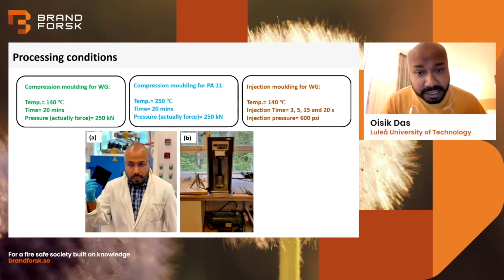So there are different processing conditions for this, where for the compression molding, we have 140 degrees, pressing time was 20 minutes, and the pressure was, well, actually its force was 250 kilonewton. For polyamide 11, we have used 250 degrees centigrade. This depends on the melting point of the plastic. We have to choose a processing temperature which is equal to or higher than the melting point of the plastic we are processing. So for polyamide 11 or nylon 11, we chose 250 degrees centigrade. The pressing time was the same, and the pressure was also the same.